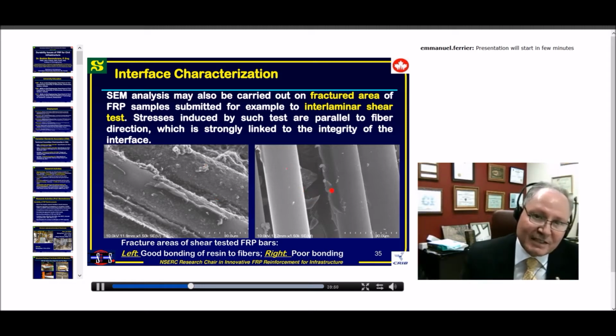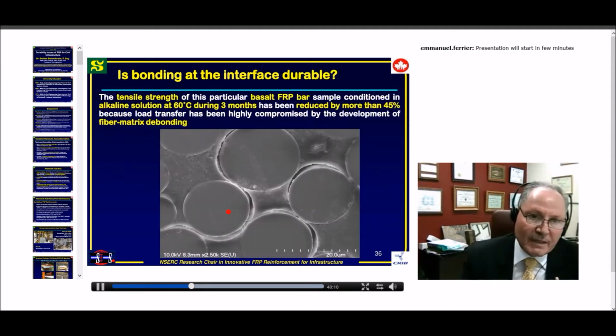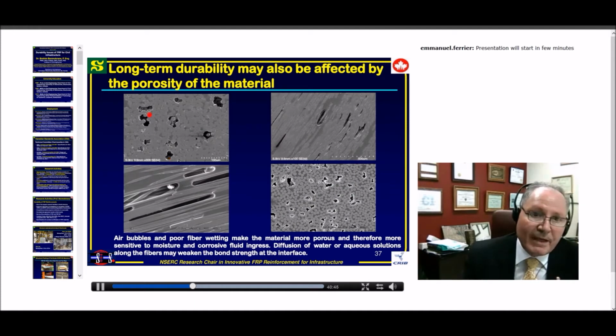This will really explain it to you. When we are testing basalt, for example, this is the kind of picture that you can have. And when you are testing glass with vinyl ester, this is the kind of picture that you get. Also when we are testing carbon with epoxy, which has good compatibility with carbon fibers. But this is also what happens at the interface when you have a problem with the interface, and this is with basalt bars. This picture comes from one bar sample conditioned in alkaline solution at 60 Celsius for 3 months, and the strength was reduced by more than 45%. You can see here the fibers debonding, and it induced the huge strength decrease.